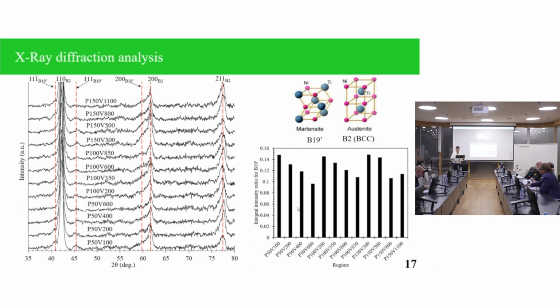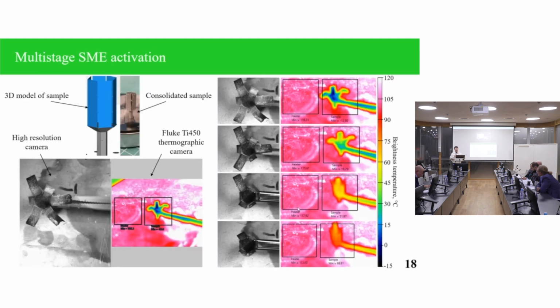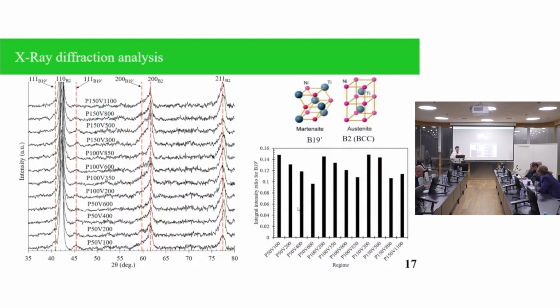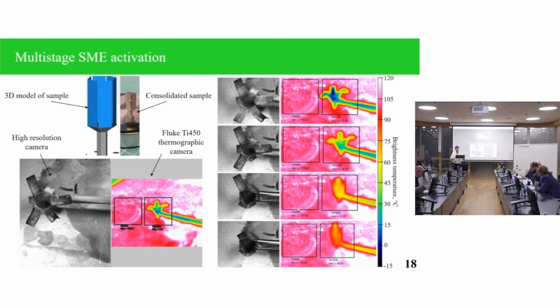Thank you for your comment. First of all, I want to say that functional properties in terms of NiTi mean the shape memory effect or superelasticity. So by tailoring the functional properties, it means that we can locally control the temperature of the shape memory effect, the temperature when the shape memory effect appears, or we can receive superelasticity in the as-built condition. In terms of control of the temperature for the shape memory effect to appear, this experiment was performed. It was demonstrated experimentally that different parts of the same sample manufactured by laser powder bed fusion can exhibit different temperatures of shape memory effect activation. That means tailoring of functional properties.